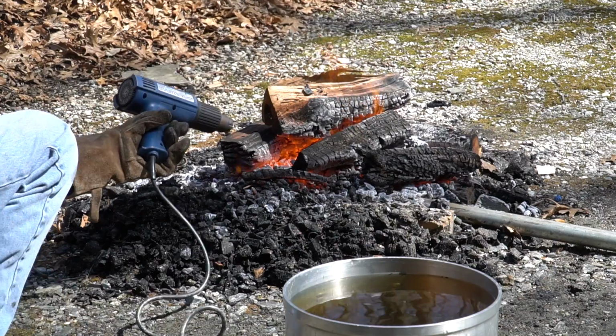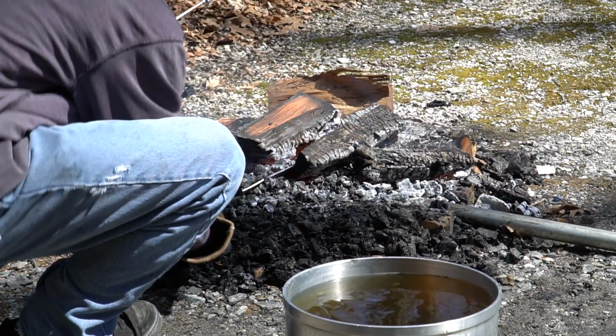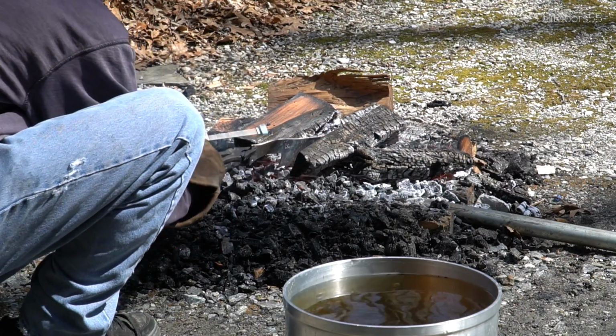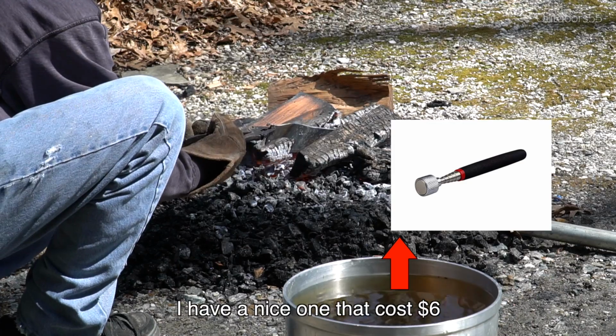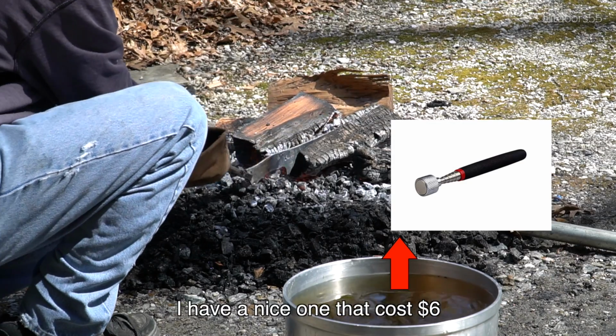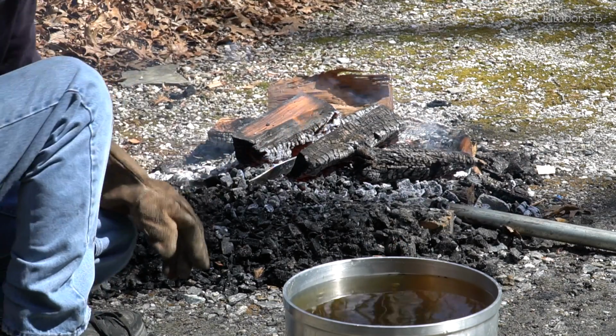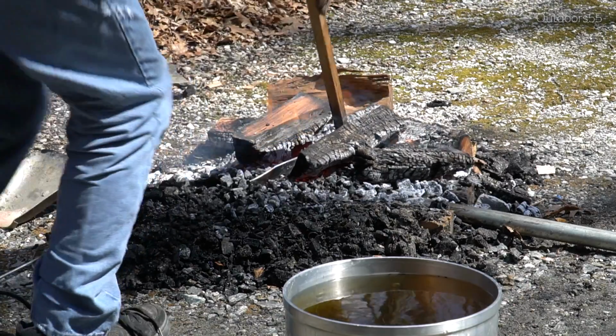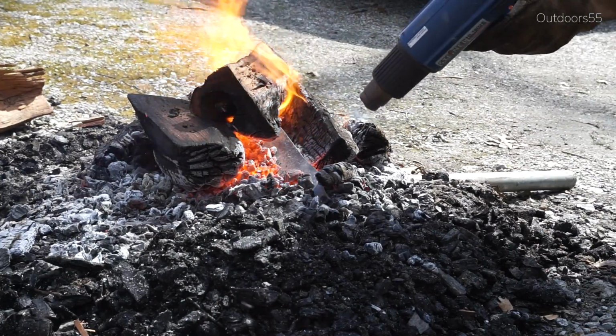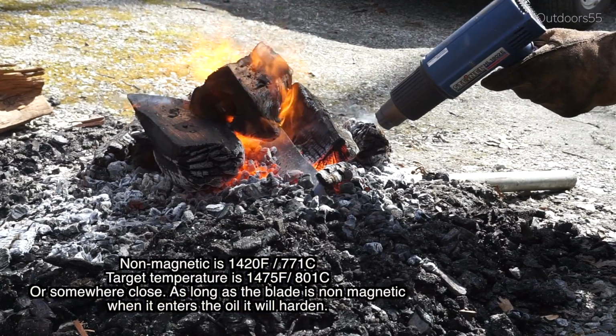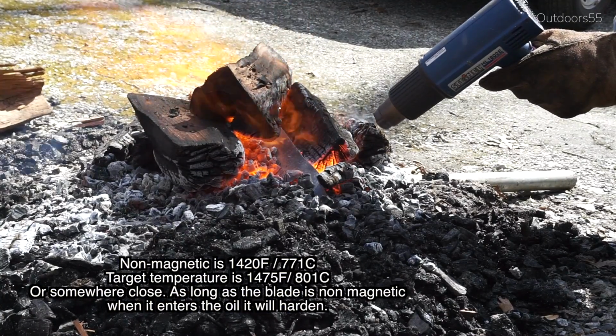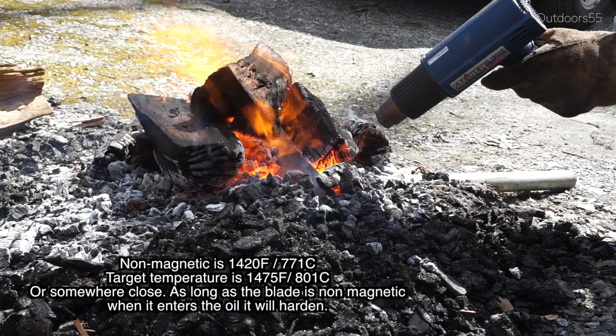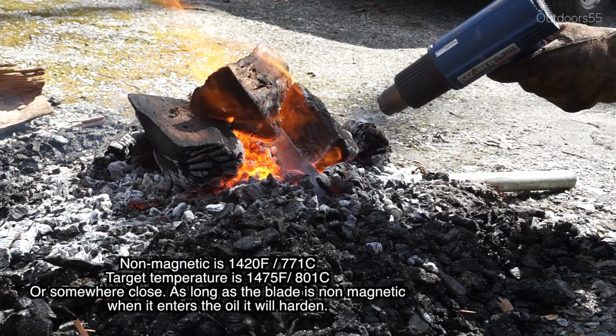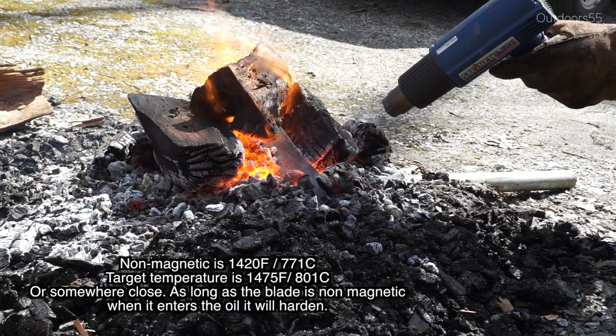Well, essentially what you need is a magnet on a long stick, or one of those little things that extends like I have. You can pick them up for like $1 or something, again at the dollar store. They work really well. And what you want to do is heat this blade up until the entire cutting edge becomes non-magnetic. So the best thing to do is to heat the entire cutting edge up to non-magnetic, then put it back on the heat for a minute or so to get a little bit of extra heat into the steel, and then do your quench.